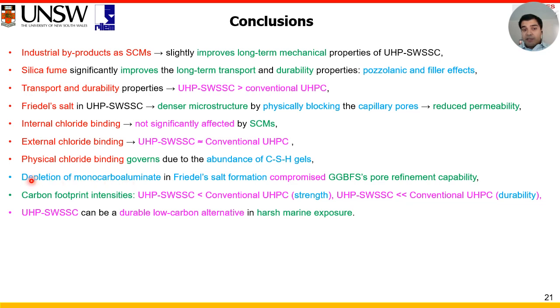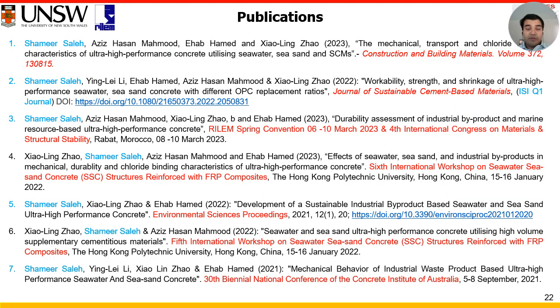Monocarboaluminate depletes and thus compromises the slag's pore refinement capability. Also, in terms of carbon footprint intensity, marine UHPC is a lot better than conventional UHPC. So we can say that marine UHPC can be a durable, low carbon alternative compared to conventional UHPC.